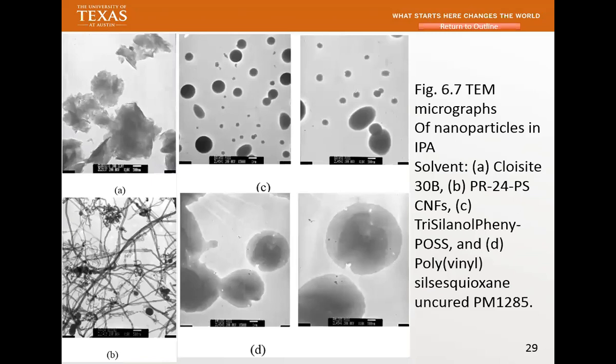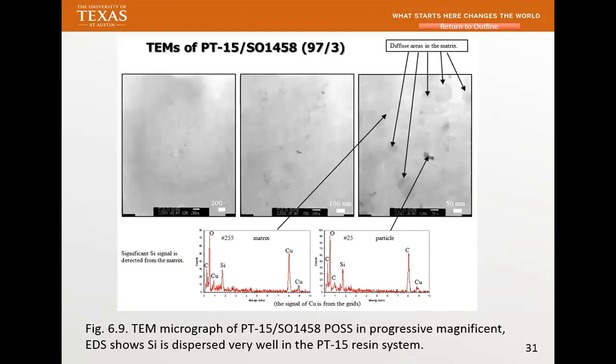This is POSS. When they sell it to me, they say it's a nanoparticle. When I look at them, well, these are actually micron. They're very large. But the trick is, if you use the right one, and I'll show you an example, with the right surface treatment, it will turn into nanoparticles. Okay? So this is an example. This is something we did. There's a PT-15 vinyl ester, and vinyl ester is one of the resin systems we use. We put this POSS in there.